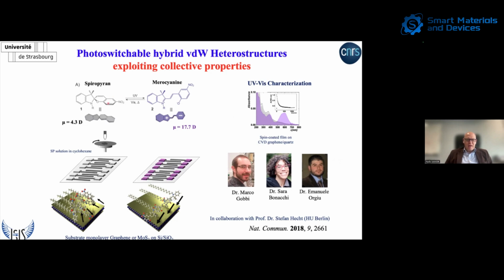And so this spiropyran has, as its R group, a very long linear alkyl chain of 18 carbon atoms, so an octadecyl chain. This forces the molecule to assemble into this lamella structure, and therefore we are positioning with atomic precision the spiropyran unit on the basal plane of the graphene, and later also of molybdenum disulfide, making dry films by spin coating that can be isomerized to the merocyanine form with UV light illumination.